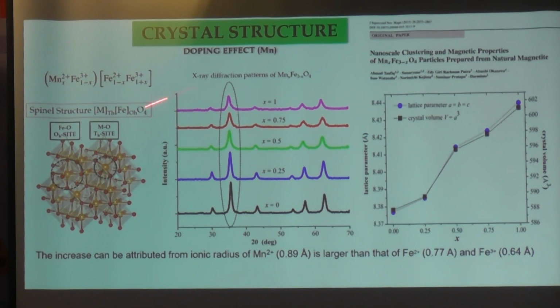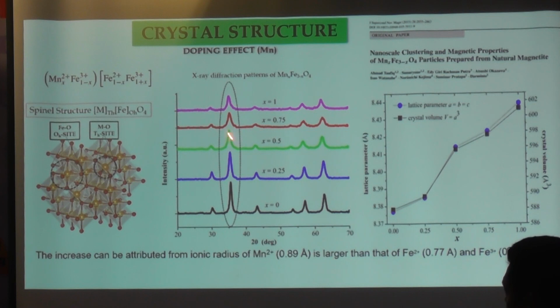And the second one, this is the magnetite doped by manganese from 0 until 1 in molar ratio. We can see in here the higher the manganese composition, the lower the intensity, and also there is a shifting peak from the higher 2 theta position to the lower position. It means that the doping or substitution process of Mn replacing iron has been successfully achieved.